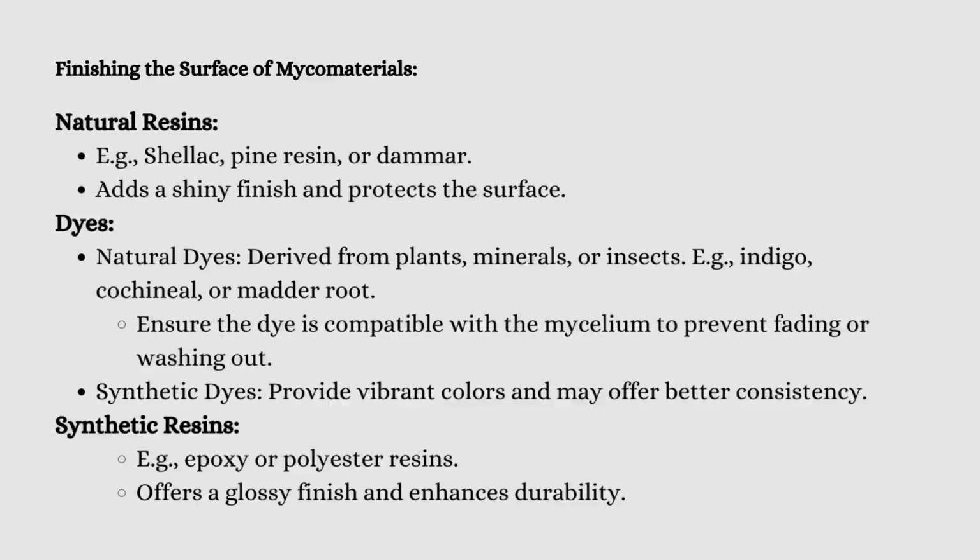And in this case, some of the ways that you can do your finishes is by using a natural resin. In the video in this module of this course, I shared with you some different kinds of resins and what they look like. We have experimented with everything from synthetic resins to using pine resin, which is only soluble in alcohol. That's important to note. A lot of these tree resins, even Arabic gum, are not normally soluble in water.